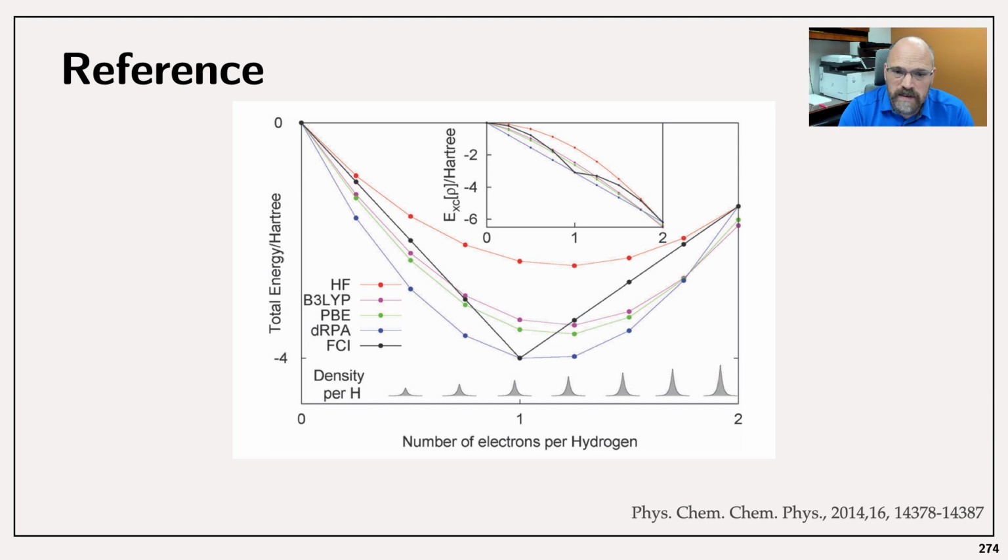If you had just one thing to remember, it is that yes, the band gap in LDA is not great, because we are missing this discontinuity in the first derivative of the exchange correlation energy with respect to the number of electrons. That's basically the reason for that. It is not just because DFT is a ground state theory, or because Kohn-Sham orbitals are no good. That's not the reason. If we had the exact exchange correlation functional, we could calculate the band gap.